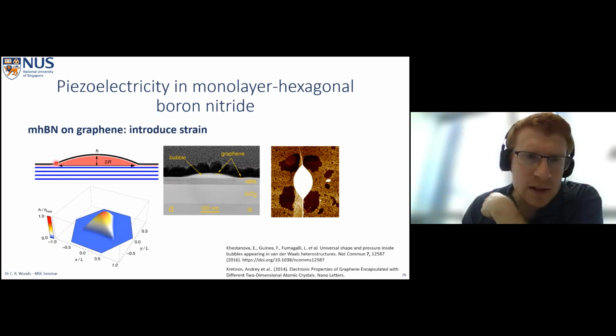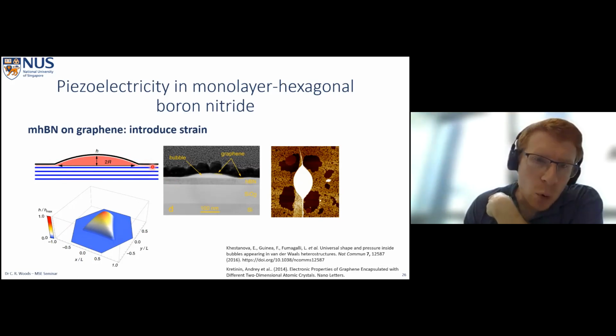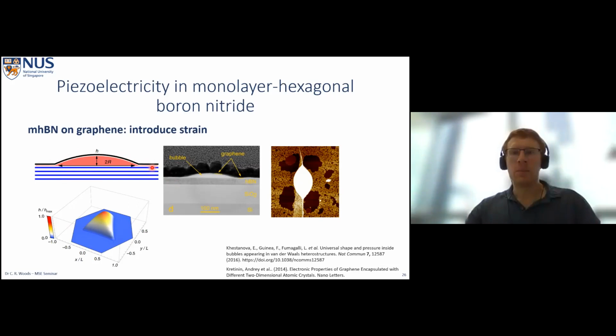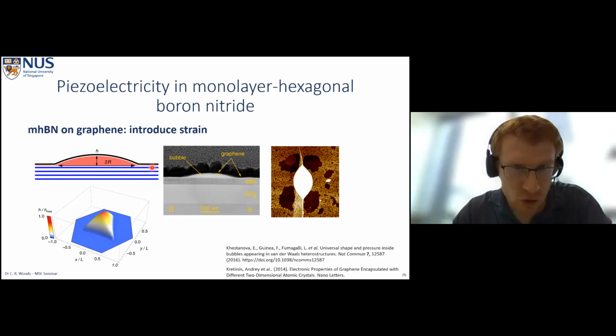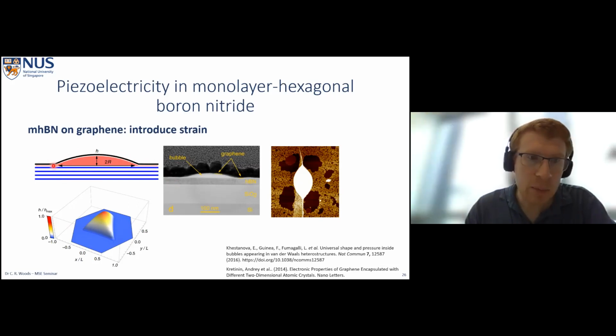It's an interesting question though, because boron nitride has a slightly weaker Young's modulus, you might expect to see something in the region around, as both layers will try to relax the strain. So you might see something, but I would certainly expect it to be a more pronounced effect when the monolayer is on top, when it is the second one to be deposited, because then the emphasis is on the monolayer boron nitride to accommodate more of the strain. So I hope that answers the question.